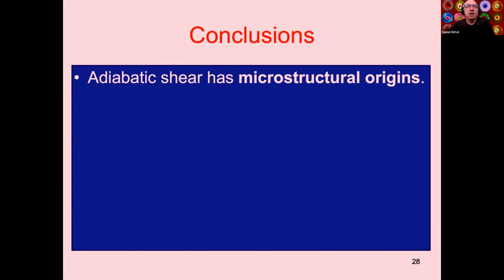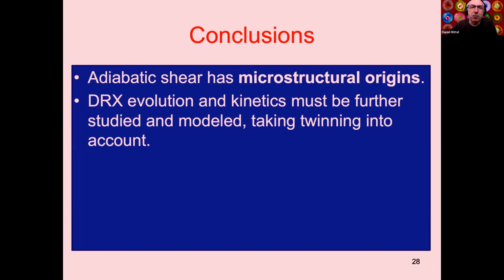Conclusions. Adiabatic shear has, first and foremost, microstructural origins. That's what we believe. The evolution of dynamic recrystallization and kinetics must be further studied, and the interaction with twinning must be taken into account.